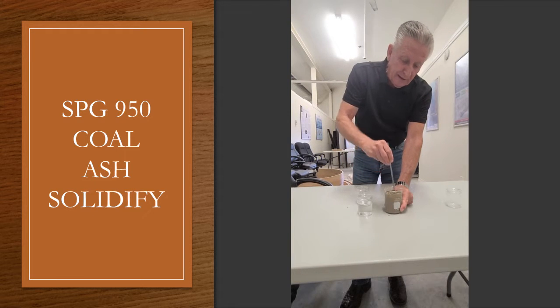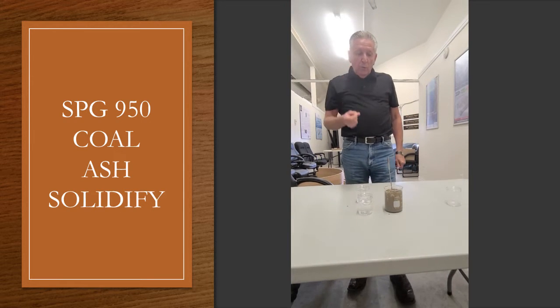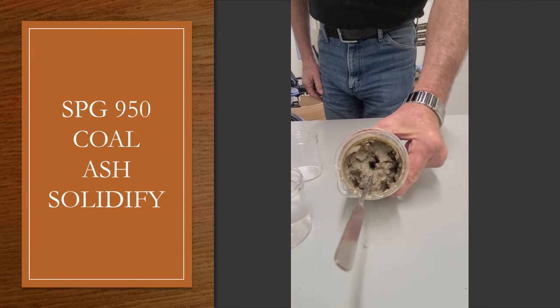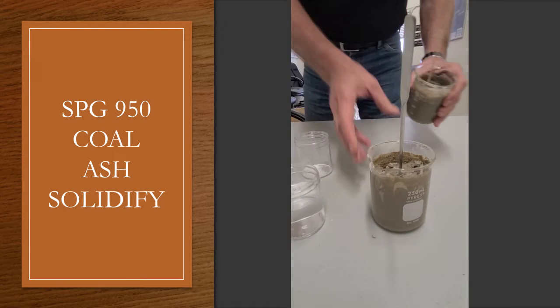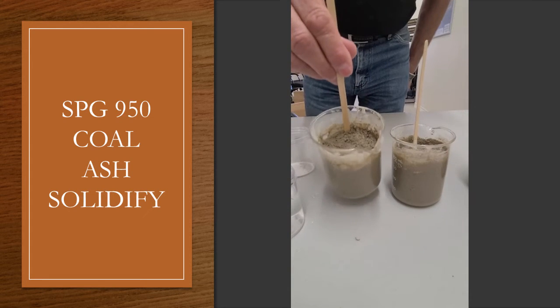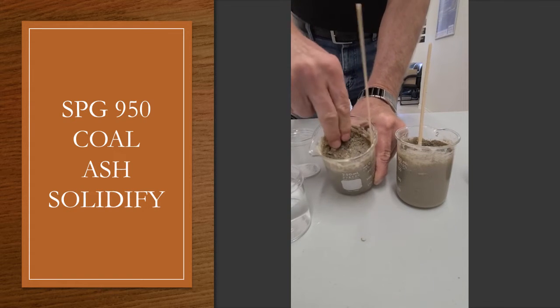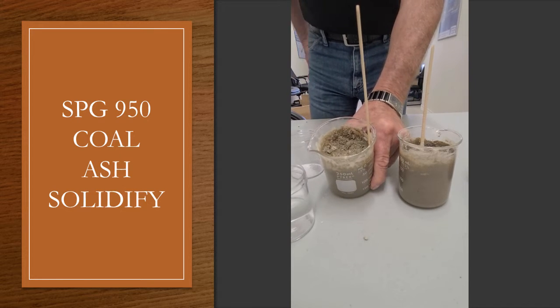This sample is approximately 28% moisture added to what was already a liquefied fly ash. You can see it's been only 30 seconds or so and it's already solidified. What will happen over the next day or so, we'll end up with a product that looks like this — which is basically completely solidified and actually at a packable compaction surface so that it can be moved, compacted in layers, and top-filled however the environmental people suggest.